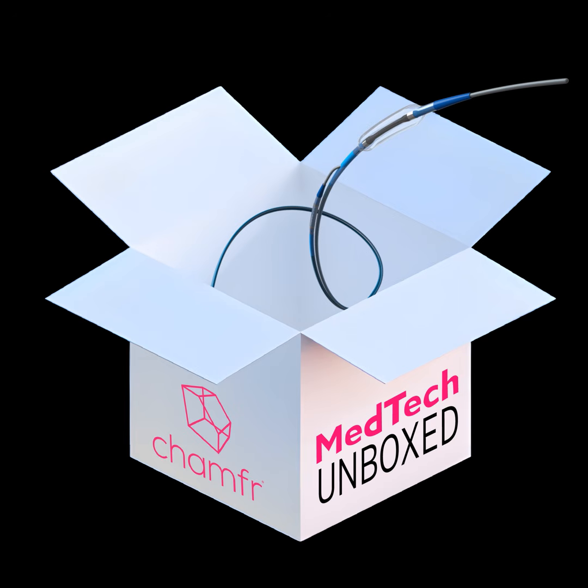But from a design and manufacturing perspective, you always have to worry about the etching, because PTFE is the most inert material. So in order to bond it, you have to use a sodium solution to etch it to basically make the surface reactive. So when that happens, if you touch it, if you stretch it, if you do anything to it, it will tend to lose its edge. And when you try to finish a $300, $400 catheter in the final step, and then it gives you delamination, then you have to toss it away. That not only increases the material cost, but the overall manufacturing cost. Because if you have to scrap one catheter, then it's almost enough money to buy half a lot of material, a third of a lot of material.